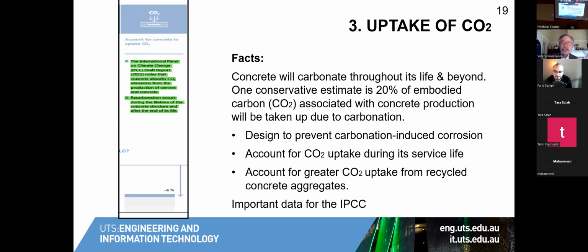Now, that's the bulk of my explanation. The other 6% I mentioned at the beginning as the pathway to reduce our carbon is that of uptake of CO2 into the concrete. Traditionally, we've been looking at carbonation as a devil because it may lead to carbonation-induced corrosion, as I have just shared with you earlier in terms of specification. But with the appropriate specification, we can actually make use of carbonation because, in a way, the concrete structure is the base carbon dioxide sink, carbon sink.